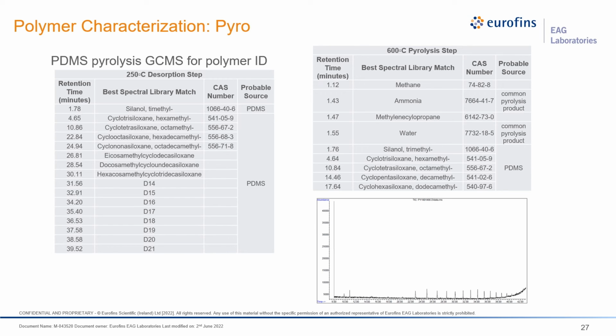Here again, we detect some common small pyrolysis products, but again, the primary peaks that we're detecting are all siloxane related. So this again further solidifies the fact that we don't think there's any prominent additives as well as any other copolymers present in the soft part of this sample.